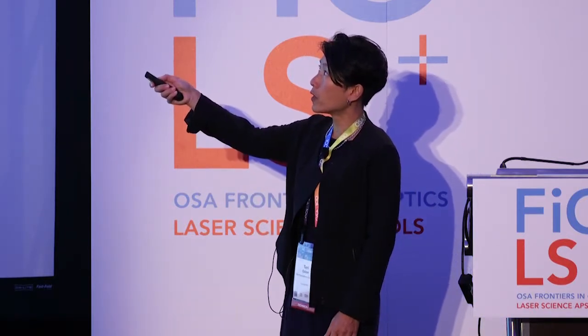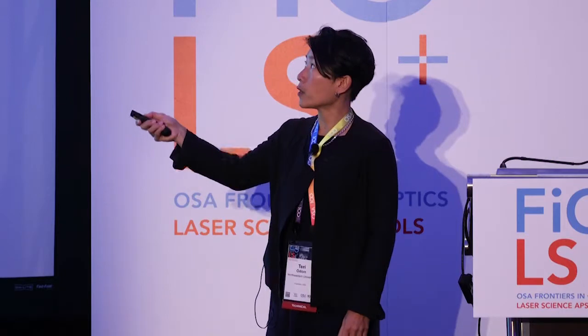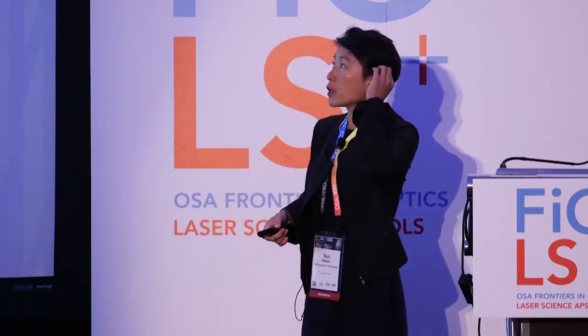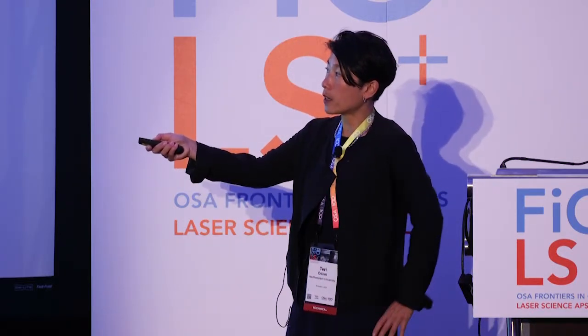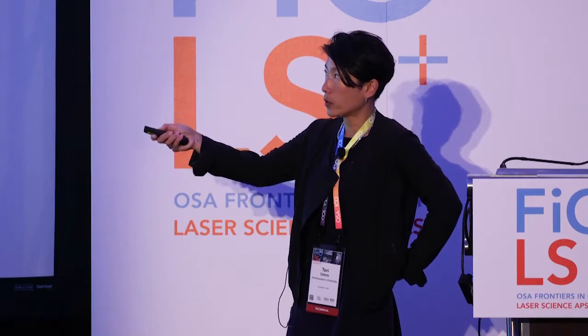So what we're interested in is taking advantage of the plasmonics, meaning there are very high local fields around the particles, as well as taking advantage of the photonics, where you can start to get these really high quality resonances. So these are sort of hybrid modes. Okay, so my group is interested in developing new types of manufacturing or scaling up patterning ways to produce these over, at least in the academic setting, large areas. This is a scanning electron micrograph of what these particles look like. These are the dimensions, and you can see that they're patterned over about a square inch.